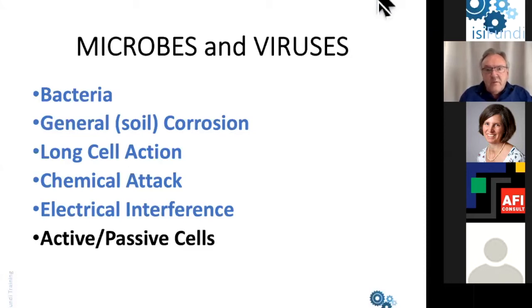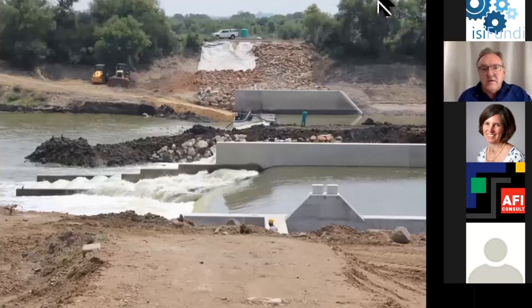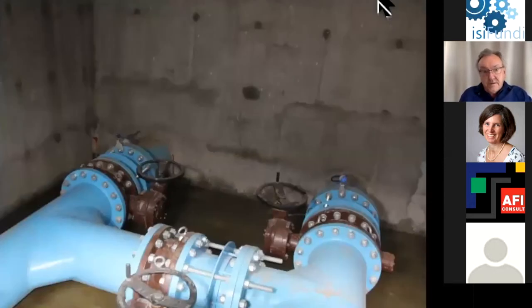Another common problem that we come across is that of what we term active and passive cells. This is a situation where the steel is in 2 chemically different situations, one of which does not corrode due to the chemical environment. And the most common situation is that of concrete encasement. Now, this is a river crossing of a fairly significant river, and the pipeline underneath this weir is encased in concrete over its entire distance. At the point where it comes out from the crossing, the pipeline will traverse into soil. So on the one side, we have steel in concrete, on the other side, we have steel in soil, and these are 2 very different electrochemical situations.